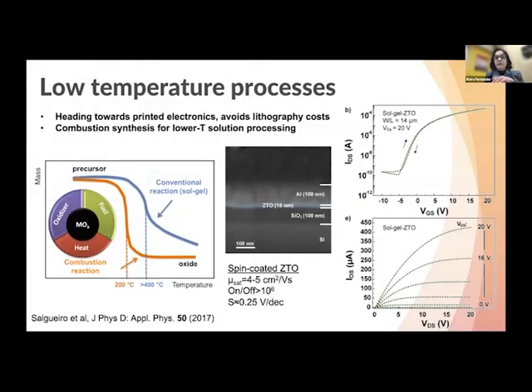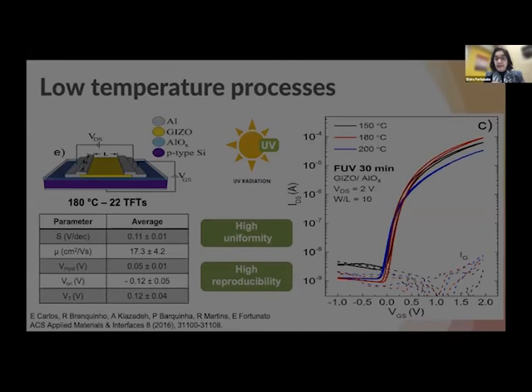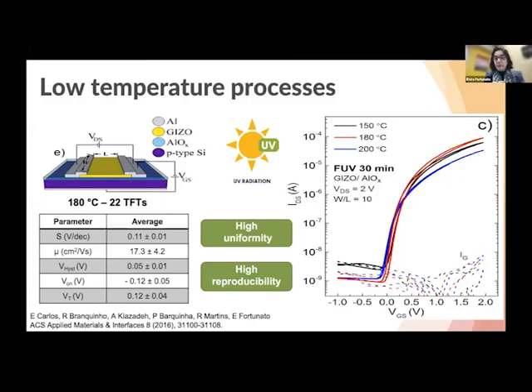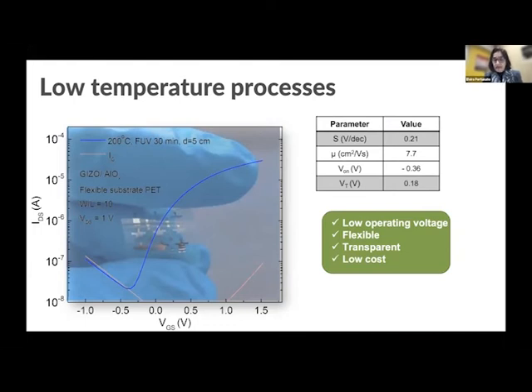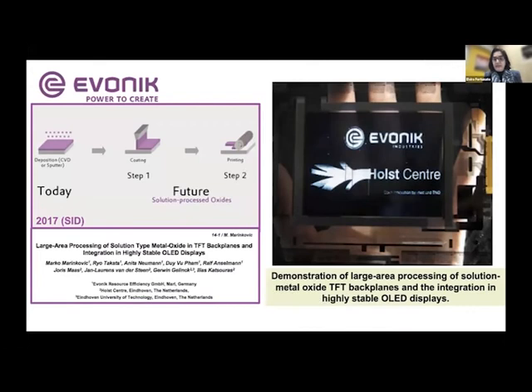And of course, since we are looking for low temperature processes, instead of using a conventional reaction based on sol gel, we are now using a combustion reaction. In that way, if we add, besides the temperature, the UV radiation, we can decrease the final deposition temperature by more than 200 degrees. Here an example of a thin film transistor, and the final deposition temperature was just 150 degrees, which is compatible with the use, for example, of plastic substrates or even paper. Again, this is an example presented by Evonik, a company where all the layers we need to produce a display have been done using a printing process.